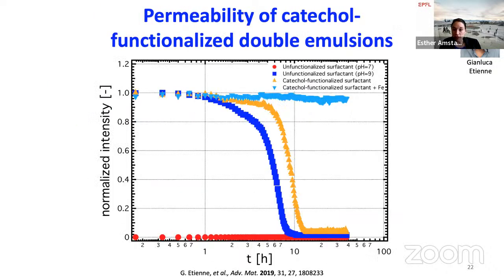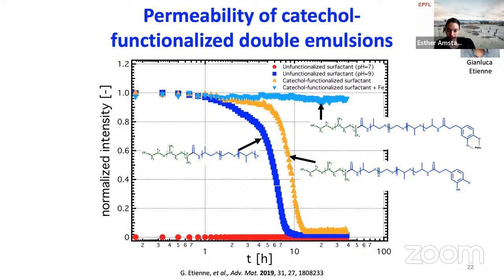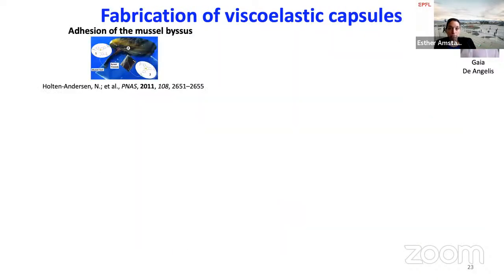And of course, if you ionically cross-link, you completely suppress the transport of any reagents across these shells for as long as the shell is stable, which depends on the pH and the ions that you use to cross-link. But this is then, to me, the safer method to completely suppress uncontrolled transport of reagents across oil phases on the long term.